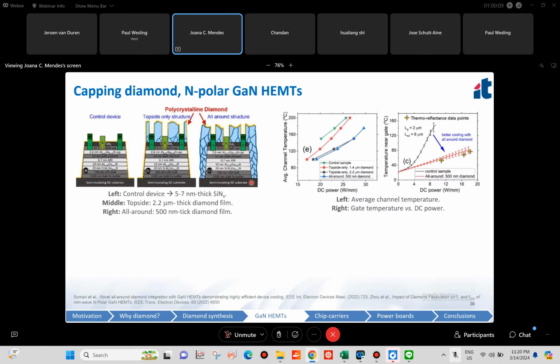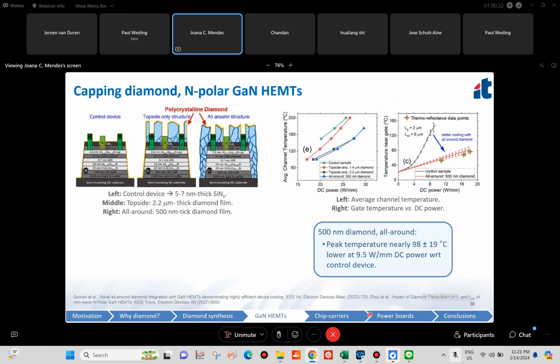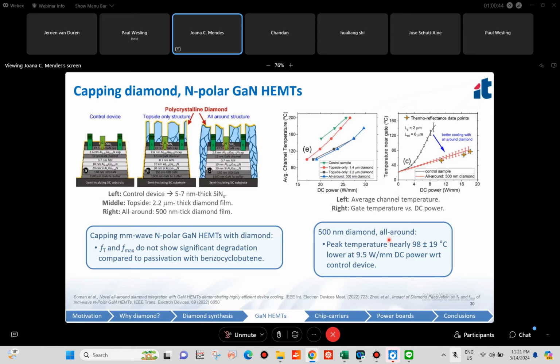And they got very interesting results. So for 25 watt per millimeter DC power, they managed to decrease the average channel temperature by around 80 degrees using both 2.2 micron thick diamond here or the 500 nanometer thick all around diamond. And in the latter case, they reduced the peak temperature nearly 100 degrees C, plus or minus 20, at 9.5 watt per millimeter DC power with respect to the control device. And on top of that, they also verified that the cutoff frequency and the maximum frequency didn't show any significant degradation when compared to the passivation with the benzocyclobutene, a standard passivating material.